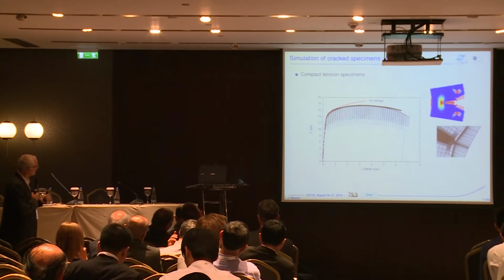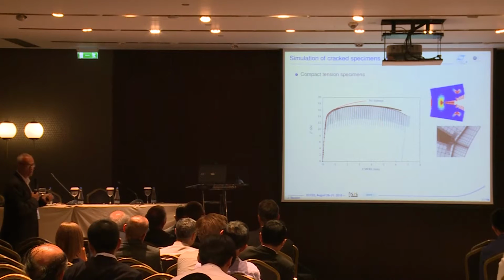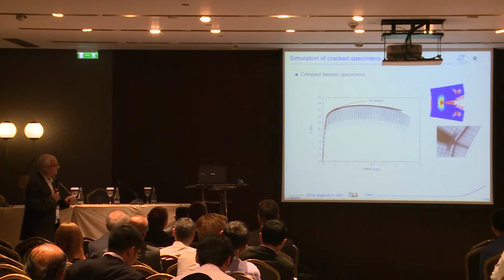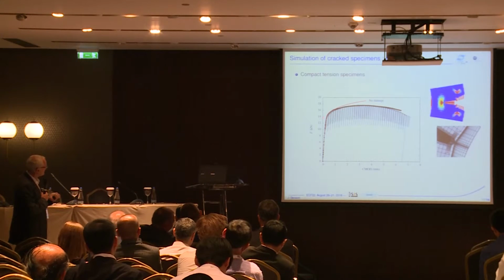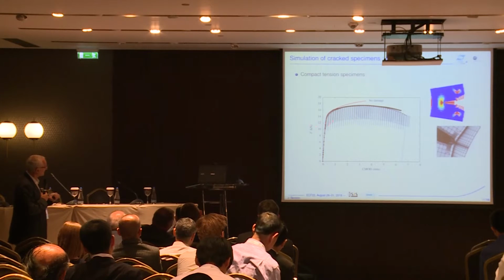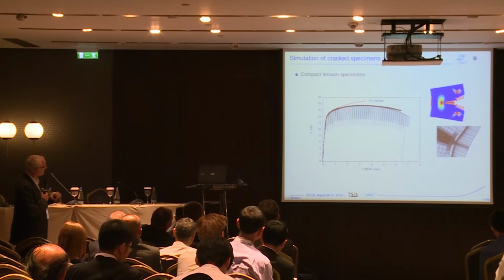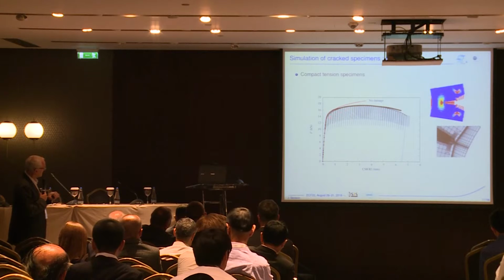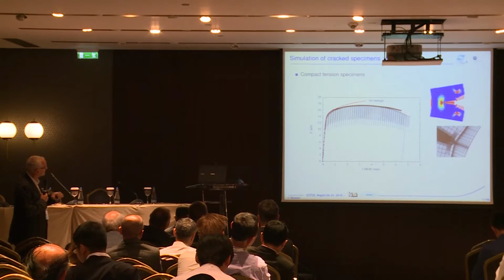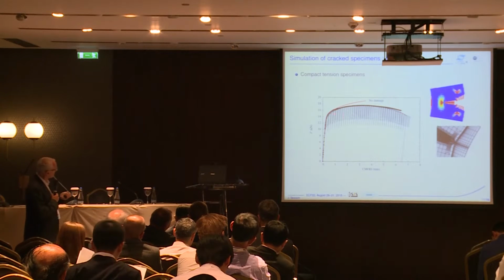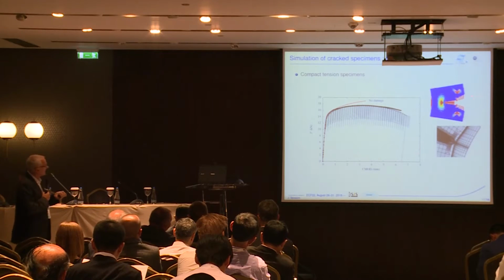So here are my two CT tests with partial unloading, which is used to evaluate crack advance. It's always interesting to get the simulation without damage. That's the red curve, which is above the experiment indeed. And the black thick curve here is the simulation, and we get a fairly good match, not as good at the end, but the beginning at least is very good.